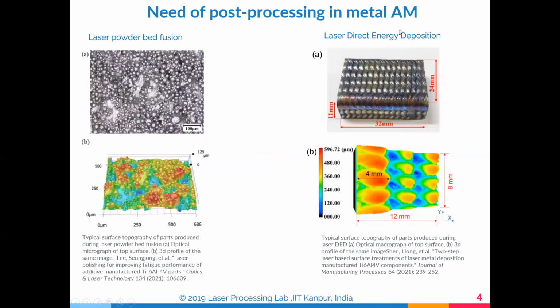When we look at the needs for post-processing, you can see the powder in one layer, how is it deposited? Sometimes the powder is not melted, sometimes the powder melts and forms globules, or galling, or balling. All these things are possible. In laser powder bed fusion you will have such spots. When you do the AFM image or the three-dimensional topography, this is 2D and this is 3D. You can see what amount of variation is there on the surface, somewhere around 129 microns, and the height will be close to 100 microns. So this is accumulation or joining of powder, then melting of powder.